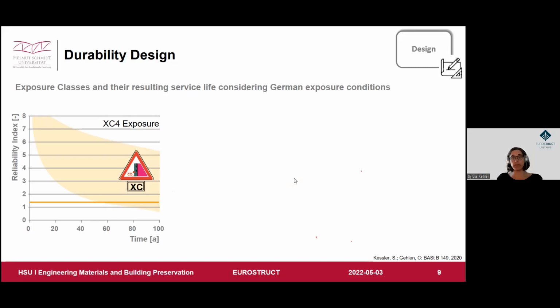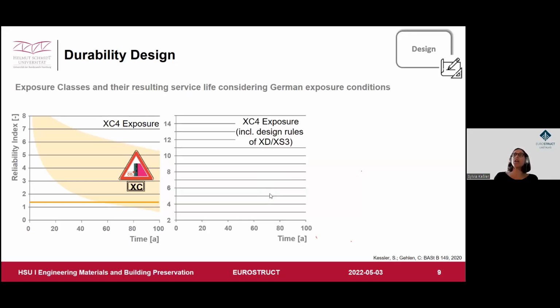Normally, if you have a reinforced concrete structure which is assigned to the exposure class XC4, especially for bridges, it is normally XD3 as well. And since XD3 requires harsher material resistances, or you have to build a better concrete, which normally also has better resistance against carbonation, we also checked the XC4 exposure under the boundary condition that XD3 is also valid. Since now we have much higher material resistances, we do not have to be concerned at all that we will have problems with carbonation-induced corrosion.